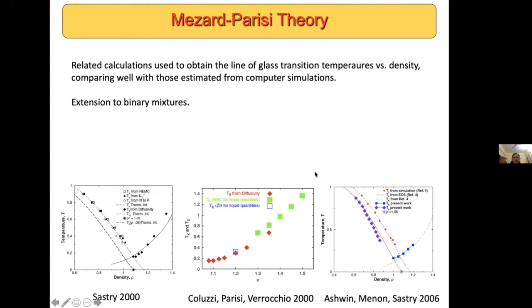This is the only slide where I can make a direct connection between some things that I've been involved with and this line of work. So I had, through simulations and looking at the inherent structure thermodynamics, evaluated a glass transition line as a function of density, which very soon after was evaluated through the schemes such as what I just mentioned, by Parisi and co-workers, finding a fairly good agreement between the glass transition line obtained from dynamics, which in that case agreed also with the thermodynamic evaluation, and from the replica theory. And we carried out some related work later on, we being Ashwin, my student, then Gautam Menon. Okay.